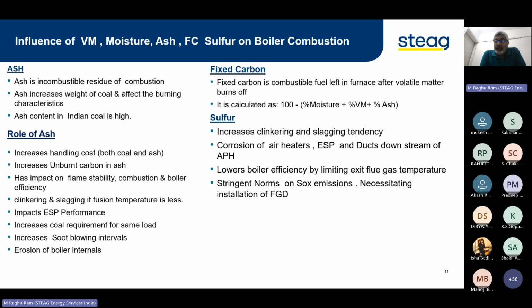And if you have anybody from CFBC boilers, they can appreciate this point. You can see the bed ash. In CFBC boilers, ash is circulated inside the combustor along with the fuel. It is a bed material which is circulated from combustor to cyclone and back to the boiler. So the erosion pattern of this bed ash on the combustor water walls is severe. We lose millimeters in some time. That's why several techniques are available right now: metal spray coating, tungsten coating, and other highly abrasion-resistant coatings, which power plants are adopting to reduce this erosion.